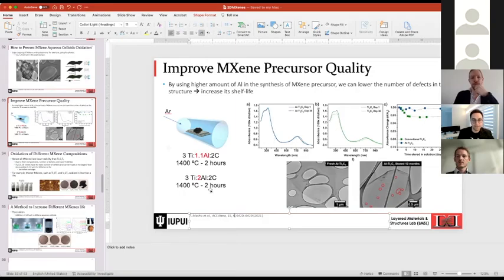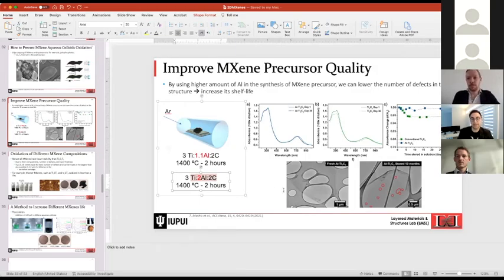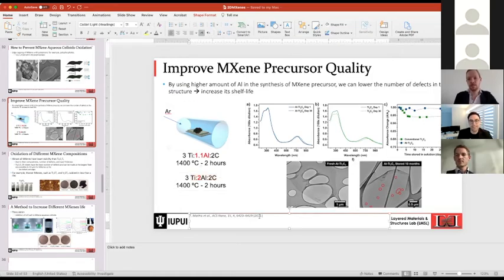And that's the reason behind the use of higher aluminum that leads to higher stability, because the resulting TiC layer of this MAX phase will have fewer defects, fewer vacancies of titanium, and that leads to higher stability. Now, as I said, this is an area for further exploration and investigation to fully understand the effect of higher usage of aluminum. And it's not fully understood yet because it's only a 1-year study, or less than that. Okay. I would say 2 more quick questions, and then the rest can ask you more specific questions via email.